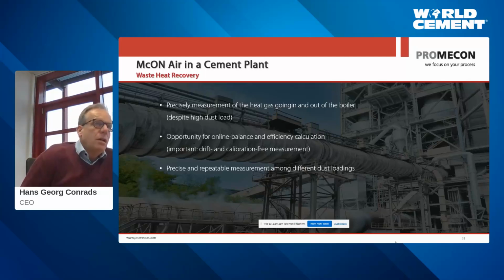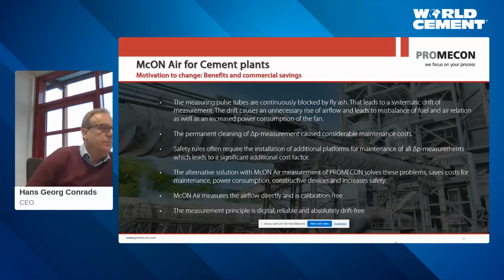In most boilers, people measure temperature, but you're missing the flow, right? So, I mean, in coal boilers, you can also measure the O2. So you measure the O2 level, and that tells you about the stoichiometry. But in a waste heat recovery boiler, you are not combusting anything. There's no combustion. So the typical O2 measurement that helps you to check the efficiency of your waste heat recovery boiler is not helping you. The only thing that's helping you is temperature and the flow. Because temperature and flow give you the enthalpy that goes into the boiler and the enthalpy that goes out of the boiler. So you can see how much energy the boiler has been able to get out of the waste heat gas.